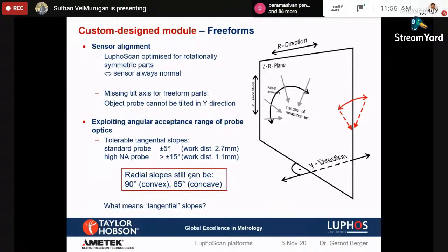the standard probe can measure it. If the customer needs any specific analysis for the free-form, we can generate only the software part of it, but the standard probe can be used. On the other side, if the free-form sample itself has more than plus or minus 15 degree slope, my standard probe will have a limitation. So we have a special probe to cover the steep slope of plus or minus 15 degrees. That can be added into the machine, and straight away they can measure it. This all depends on the application and the requirement. So we have different solutions to fulfill their needs.